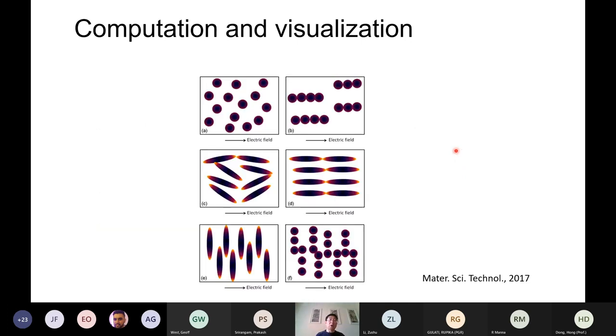So if we summarize, if we have electric current moving from left to right, and here are a lot of inclusions, in the vertical direction they will try to separate. But in the horizontal direction, if they are close enough, they may attach to each other and form a thread-wise inclusion. According to calculation, if we have those inclusions in this way and pass the electric current, they will try to align and attach to form this line.